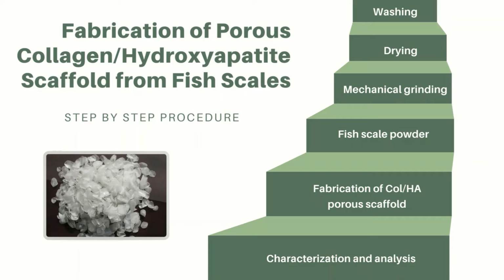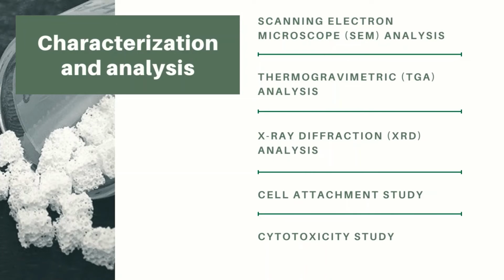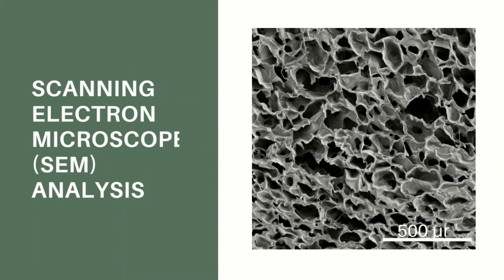The mold was left to freeze and went through a freeze-dry process to be converted into a porous scaffold. The collagen hydroxyapatite porous scaffold then went through characterization and analysis. The characterization and analysis that were done were scanning electron microscope (SEM) analysis, thermogravimetric TGA analysis, X-ray diffraction XRD analysis, cell attachment study, and cytotoxicity study.